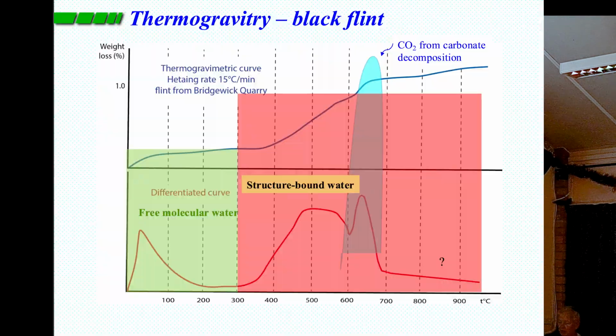This very low temperature material we see here corresponds to essentially water within the flint sample, present as liquid water. And then the main part of interest is this loss here, and that's all the structure-bound water, which leaves at a much higher temperature than the surface water, and that is bound up to the flint crystal surfaces.